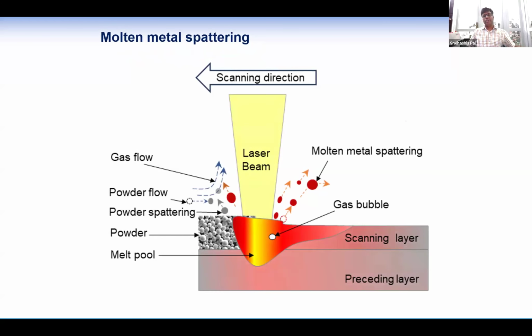So about molten metal spattering from the melt pool: when the laser falls down there, the metal powder melts and forms a melt pool. From there, if the melt pool contains some gas bubble, that can explode, so that the powder material can go out. And also, if the viscosity differs, then from the corner side of the metal, the material can go out from the action zone. Like this, a lot of material can spatter out and make a lack of material,